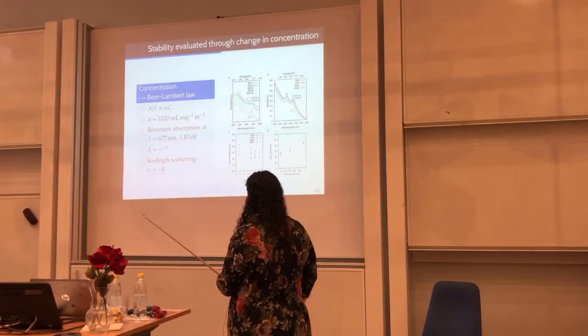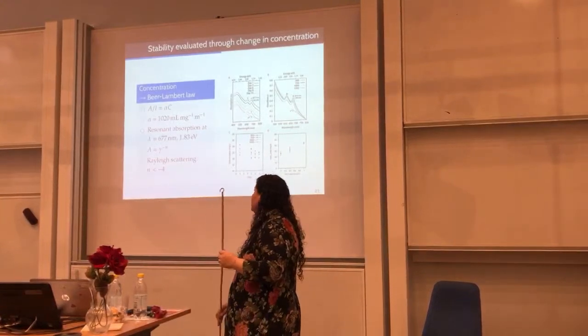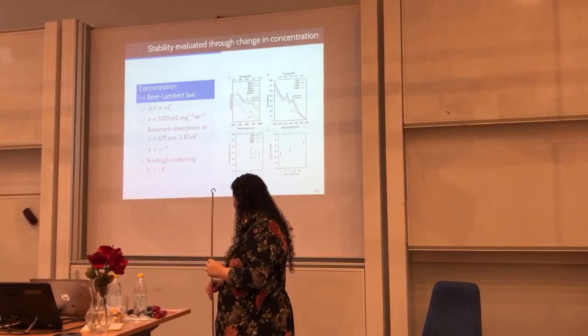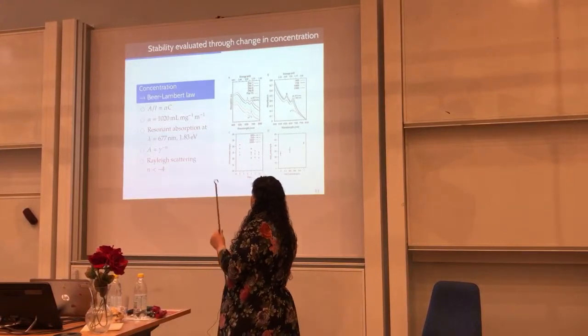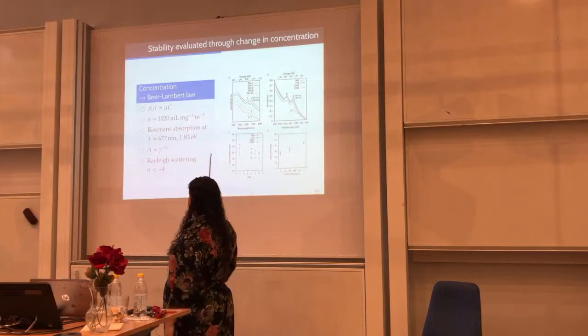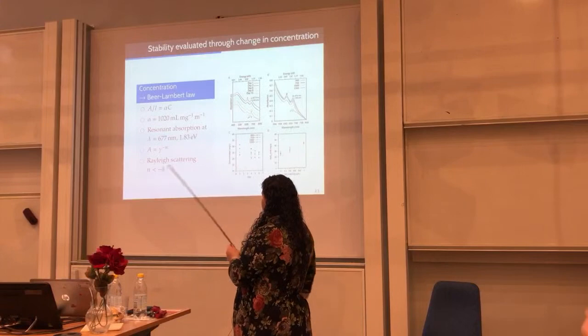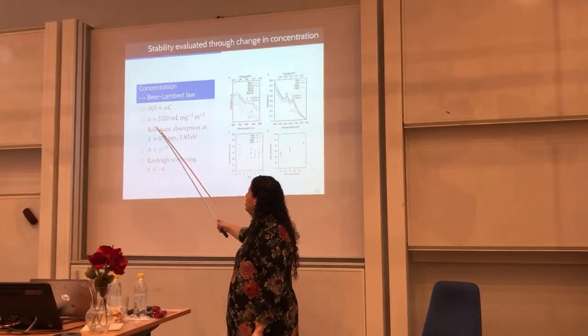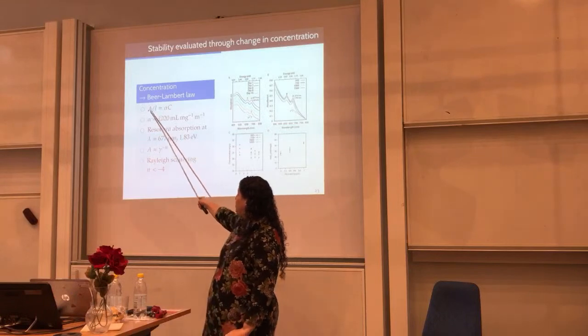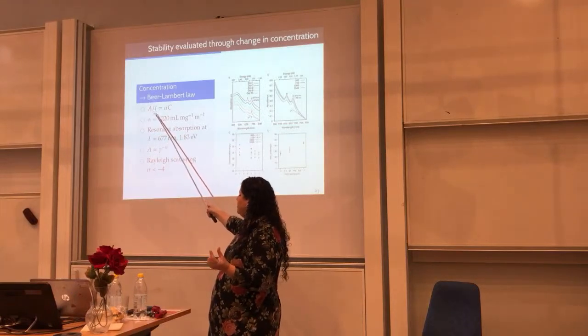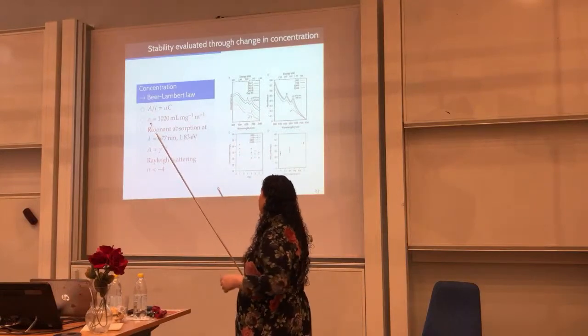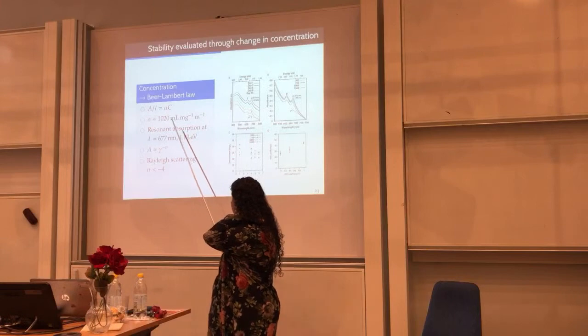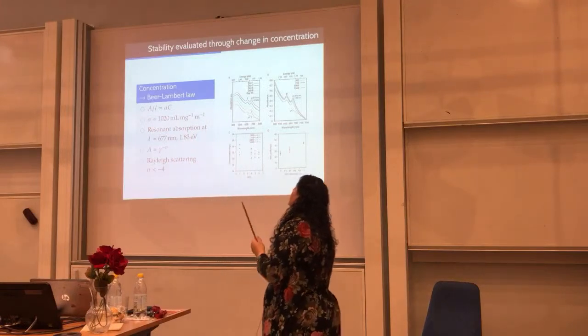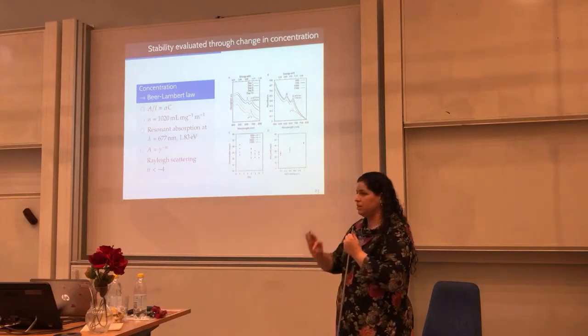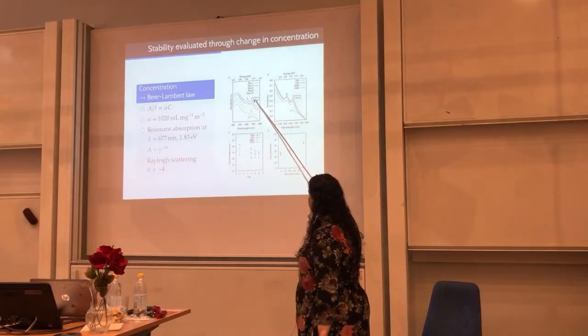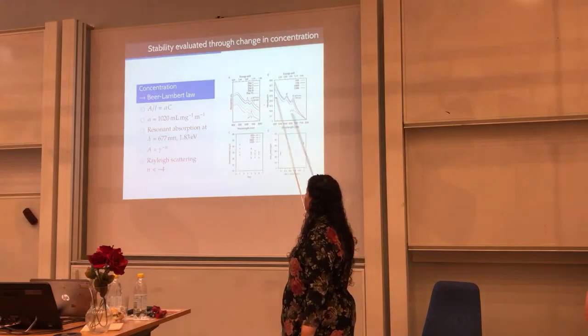The concentration of these dispersions is so small that we can measure the absorption using the Beer-Lambert law. So if we have the extinction coefficient of this material, then we measure the absorption. We know the length of the path that the light will go through when measuring this absorption. Then we can estimate the concentration. And we estimate this concentration at a particular position, at 677 nanometers, that is like 1.83 electron volts.